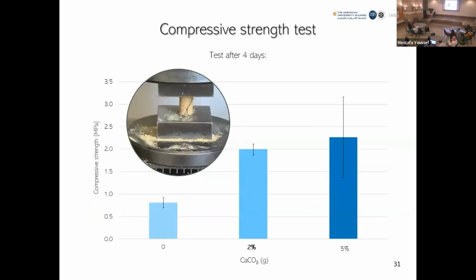And I prepared the samples. After 4 days, I was able to test all of them with a compressive strength test. As you can see here, it is possible to see a quite clear trend of increasing compressive strength as a function of the quantity of calcium carbonate put inside. All of them, in any case, always contain Portlandite. And as you can see, the sample with the higher quantity of calcium carbonate is also the sample able to reach about 2.3 megapascal in the compressive strength test.